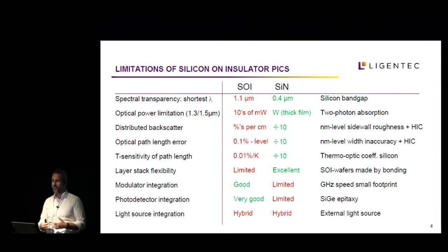And this really comes down to the physics. The band gap of a semiconductor material is a few eV, while the band gap of a dielectric material is several eV, 5 eV or even more. Second limitation is the power that these materials can handle. In silicon photonics, your power levels are a few tens of milliwatts, while in the dielectric platforms, you can really put watts. We have tested in our chips up to 7 watts CW power. Again, the physical mechanism behind is that there is no two-photon absorption and a large band gap to work with.